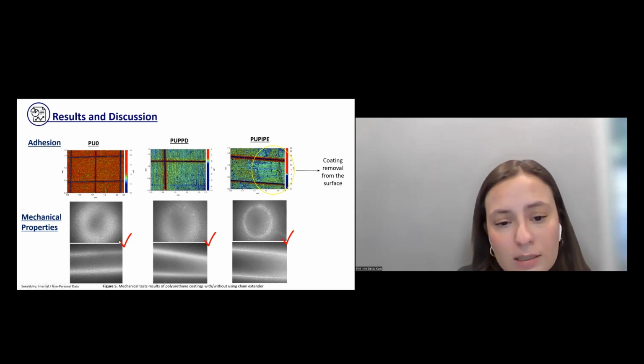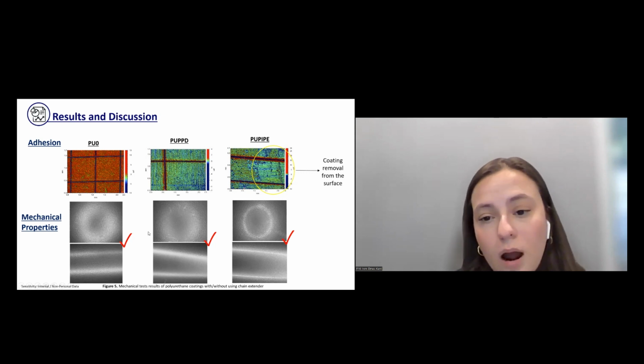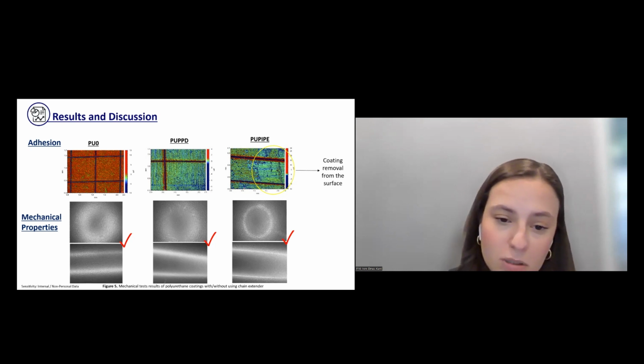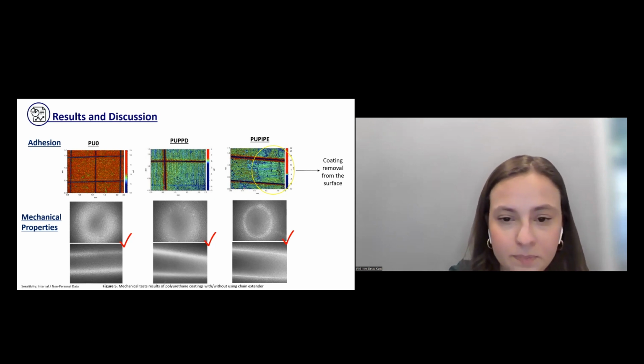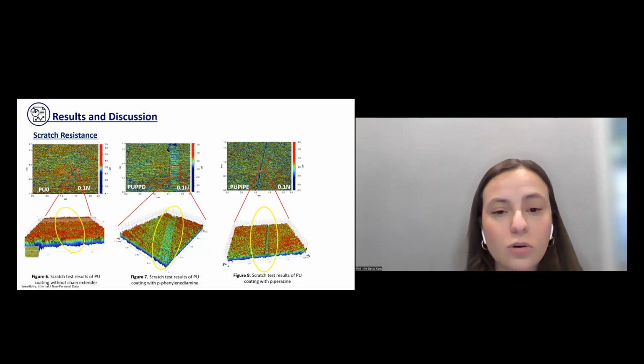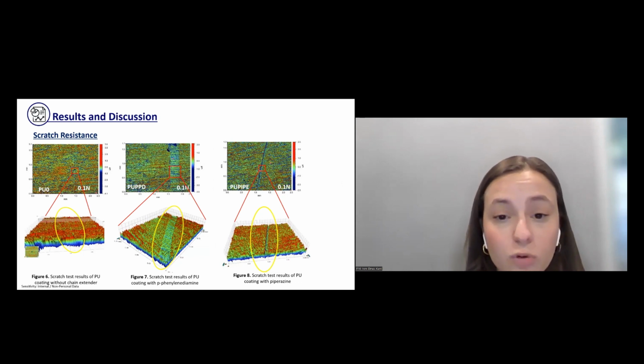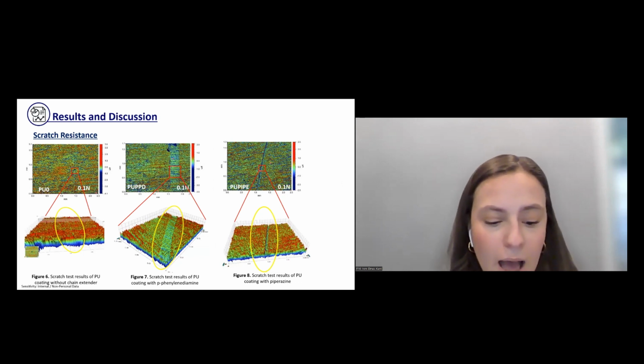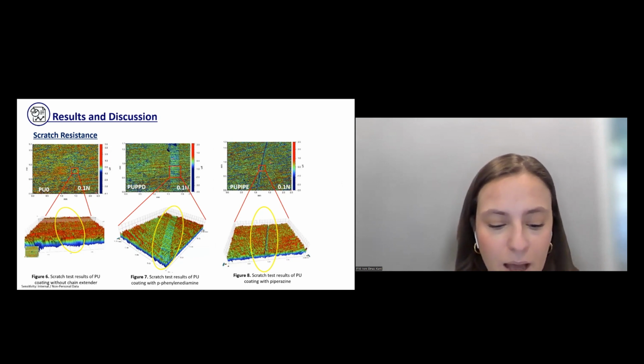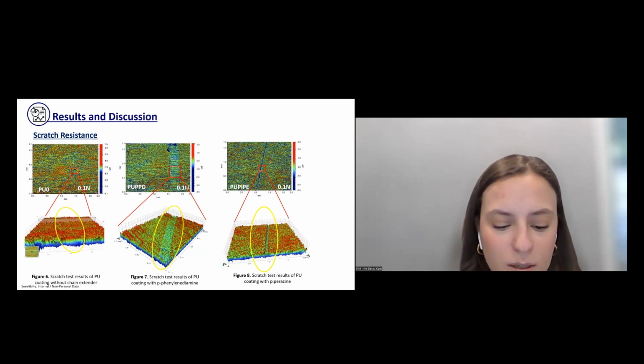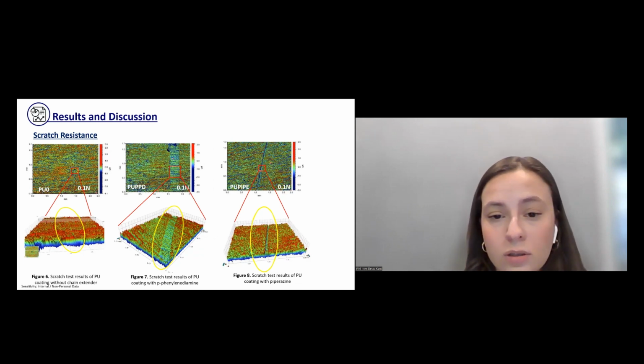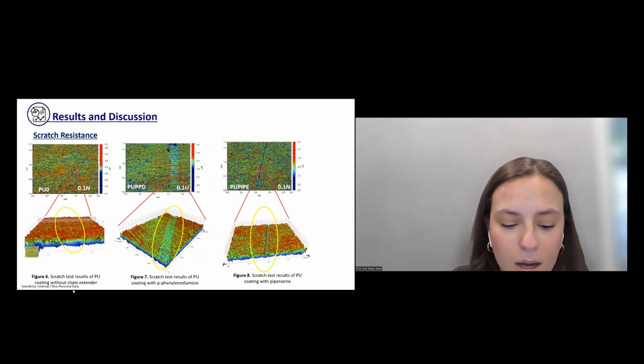Flexibility and deformation resistance tests here are not quantitative and give a qualitative indication about the hardness and toughness of the system. All the samples pass these tests. Generally, a highly cross-linked film may exhibit improved scratch resistance, but it is less flexible and much more sensitive to cracking. And although we saw a visible scratch under 0.1 Newton load on both samples, we observed a more visible and wider opening in the scratch applied to the coating containing phenylenediamine, since it is sensitive to cracking.